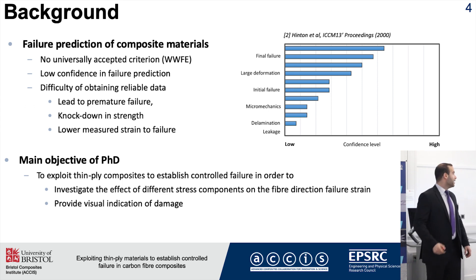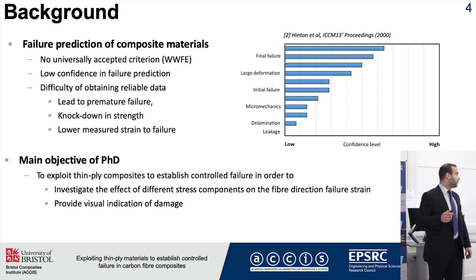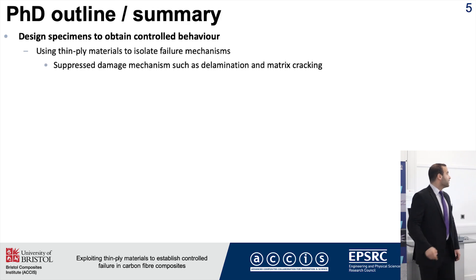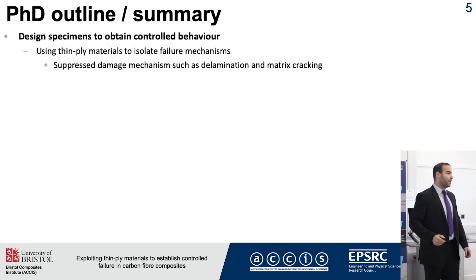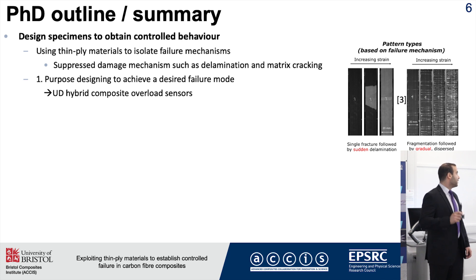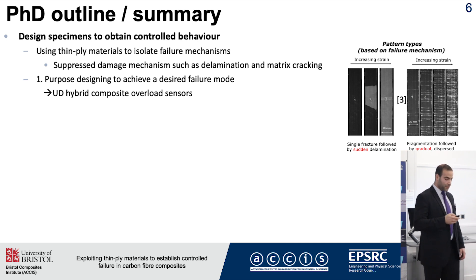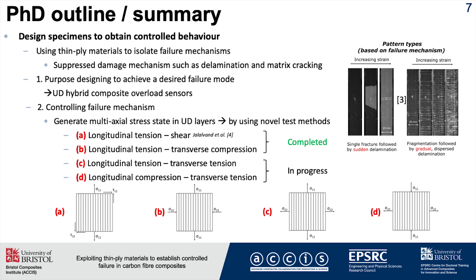The main objective of my PhD is to exploit thin ply composites to establish controlled failure for two reasons: first, to investigate the effect of different stress components on the fiber direction failure strain, and second, to provide visual indication of damage. I've been using thin ply materials mainly to isolate failure mechanisms, as thin plies are shown to suppress damage mechanisms such as delamination and matrix cracking. One project is to purposely design to achieve a desired failure mode, such as unidirectional hybrid composite overload sensors, which show a specific failure mode.